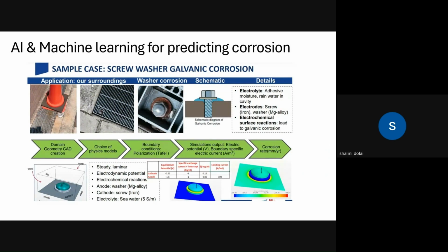And this is another case which we used in Saint Gobain. So what was happening? We wanted to use artificial intelligence to predict the corrosion. Earlier I showed you the neutral salt spray test, which takes 45 days, and even the electrochemical test has limitations. If you have big parts, you cannot measure them. Electrochemical measurements are limited to very small sizes of samples.